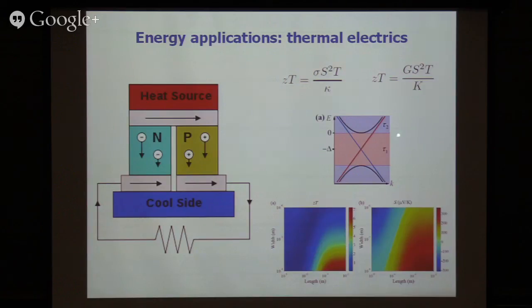But those topological surface states would have a very short lifetime above the Fermi energy because they can easily scatter into the bulk. On the other hand, they will have a very long lifetime for states below the Fermi level. So that can also increase the Seebeck coefficient. So we hope that topological insulators can be useful also as thermoelectrics. Now let me put up the last slide.